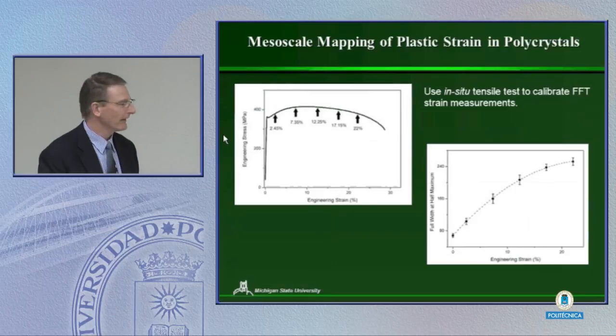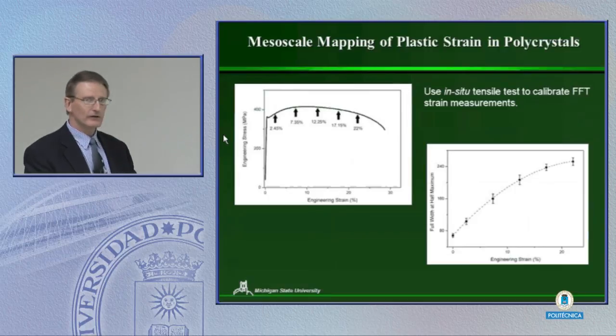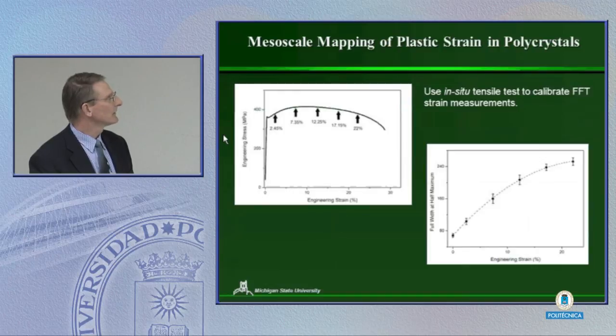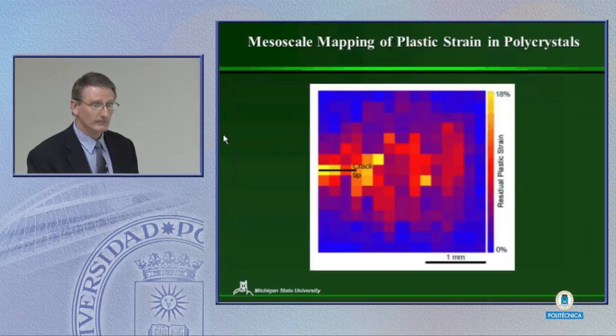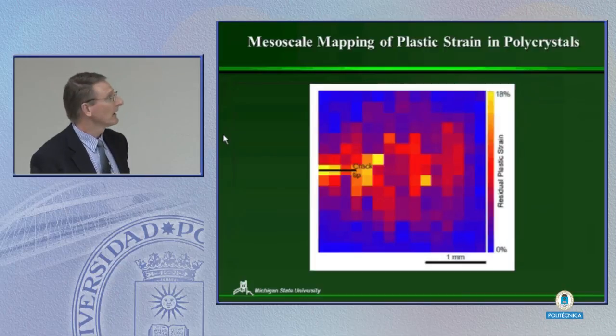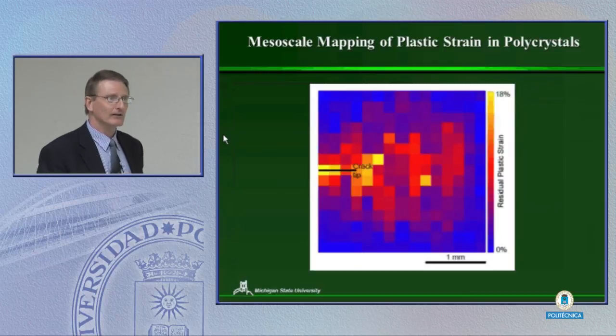So can we quantify that? Well, to quantify that, we did an in-situ straining test of the exact same material, and we measured the full width at half max on a large number of images over these different strains. And so we developed really what's just a calibration curve. Here's the full width at half max for various engineering strains. And by doing that, we were able to take this crack tip area, and again, here's 1 millimeter, and actually map out what is the strain in front of the crack tip.